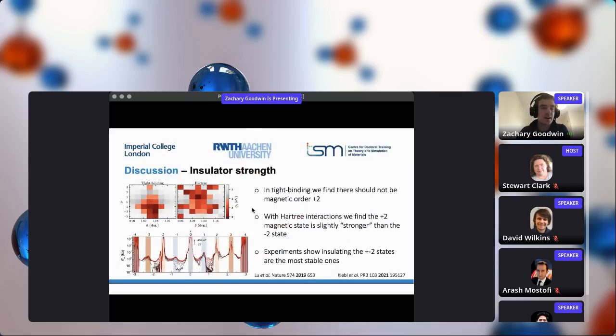Right, so we can see how well this method compares against experiments. In an experiment, as I mentioned, the insulating states at plus and minus 2 electrons per moiré unit cell are the strongest insulating states. But in our tight binding approximation, we would not expect to observe an insulating state at plus 2 electrons, which is clearly not in very good agreement with the experiments. Whereas when we keep these long-range electron interactions, we do expect magnetic order to occur at plus or minus 2 electrons per moiré unit cell. So that's clearly much better agreement than the non-interacting theory.